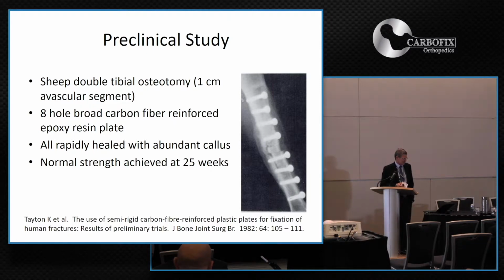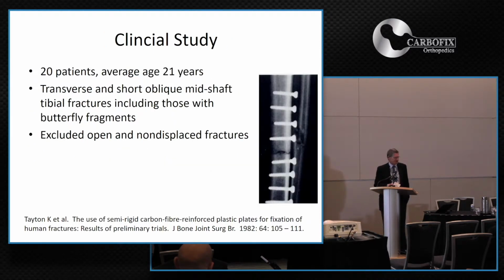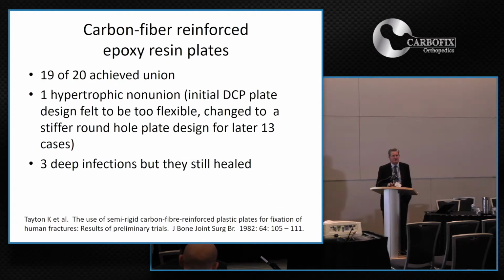And they also reported then on an early clinical study, 20 patients, average age 21 years, with a transverse or short oblique mid-shaft tibia fracture, and they excluded open fractures, so all closed fractures. 19 of 20 of these achieved union. They had one hypertrophic non-union early in the series, and they had modified the plate because they felt that their initial plate was not stiff enough, and that led to the hypertrophic non-union. They had 3 deep infections, but reported that even despite the infection, the fractures went on to unite.